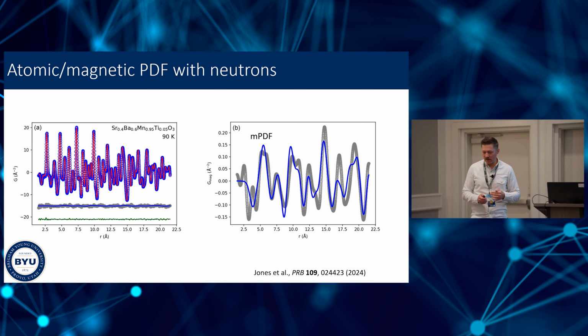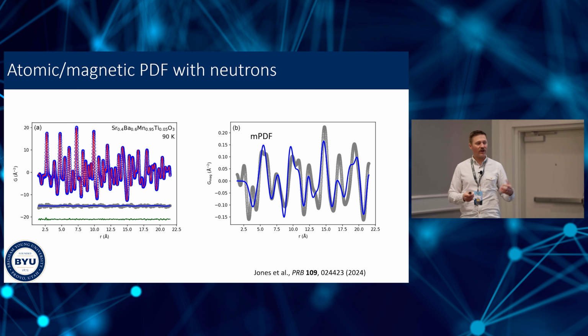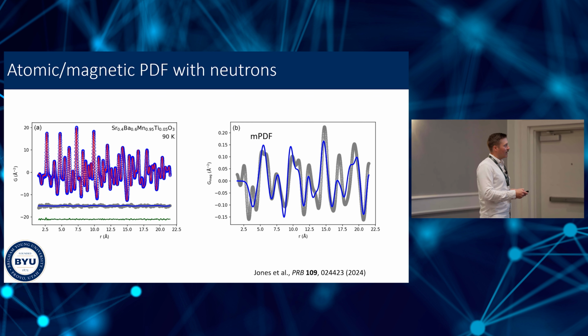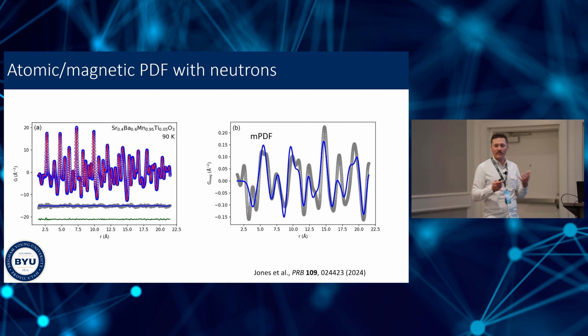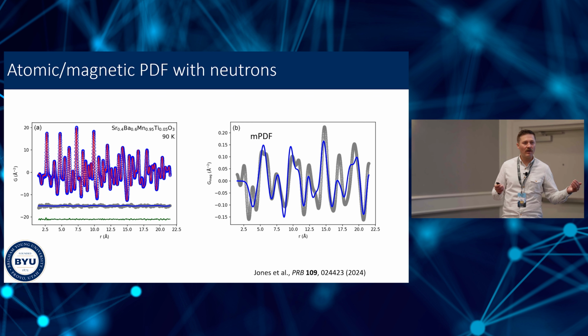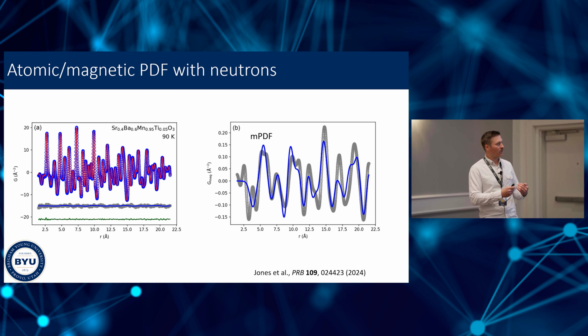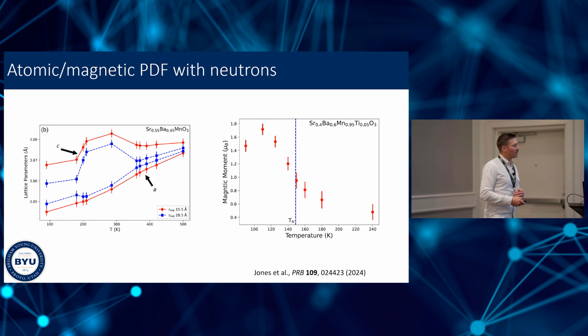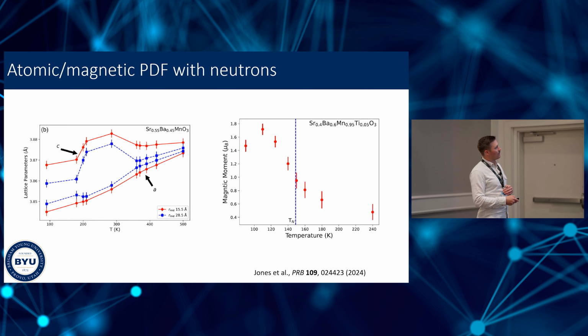So that's good. That means we can look at how these magnetic correlations change as a function of temperature in this compound. And we can play the same game that we were playing with manganese telluride, where we do these fits, we pull out a local magnetic order parameter, a correlation length, and so forth. Okay, so the results of our PDF analysis, we're looking at the lattice parameters. So C is the upper branch, A is the lower branch, and these are the difference between blue and red. These are two different fitting ranges that we used in our PDF analysis. I won't go into that too much.